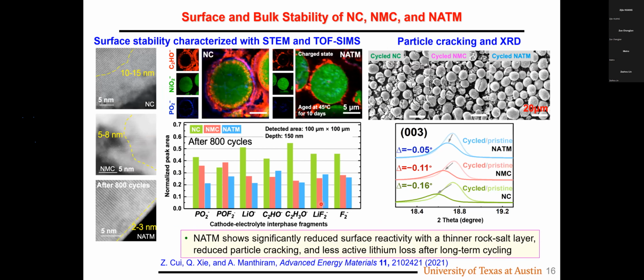I'm also showing the data in the form of a bar graph. So NC shows the highest amount of electrolyte decomposition. The red is NMC, less decomposition. NATM has the lowest electrolyte decomposition among the three materials. That is also consistent with the thicker CEI formation here with the NC, medium CEI thickness, the least CEI thickness.